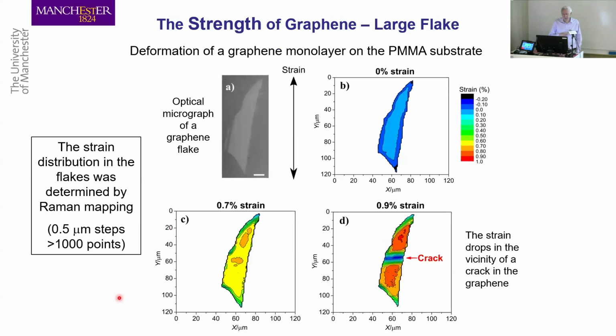Now, what I want to do is to look at the strength now. We heard of this massive strength, 130 gigapascals. Is that really the case? So we decided to try and break some flakes. So here's a flake, monolayer flake. This is probably about 50 microns long. We stretched it in the vertical direction. And then we mapped the Raman spectra over 1,000 points on the flake. So a student spent his whole Christmas measuring flakes, thousands of measurements all over these flakes to map out the strain in the flake as you deformed it.